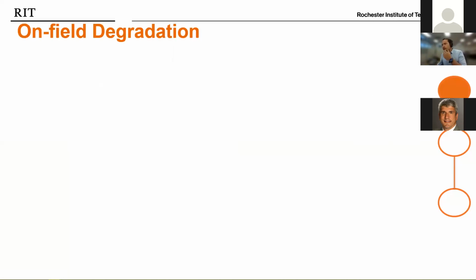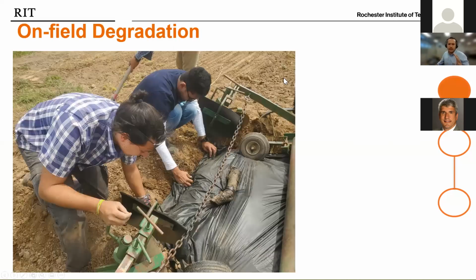So as you see, on the on-field degradation, we went in May with Harshal and worked really, really hard on laying some plastics, 3 different plastics: Film Organic, Bio360, and EcoBio. We laid them because we knew that the laying process changes the properties of the plastic. You see the wheels in that picture show that there is tension already applied to the plastic, and so maybe the degradation process is going to be different than for an untensioned sample. So we wanted to understand a little bit more the behavior of the plastics on the field. And because the main degradation indicator the literature usually uses is weight change, and that is sometimes hard to get from the field, we also wanted to explore what other indicators we could get for degradability.